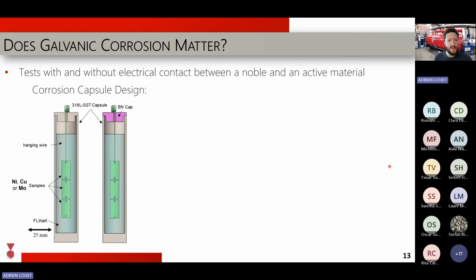Other things that we've looked at a little bit that are of interest, I wanted just to share briefly with you, is the fact that we looked at galvanic corrosion. So if we put very noble elements and we put a 316 stainless steel capsule around it, and we have electrical contact between them in the same media, we would expect the 316 stainless steel to be severely oxidized, and the coupon of nickel, copper, and moly to be very well protected against corrosion. And if we put an insulator here, we would expect this galvanic corrosion to not occur.